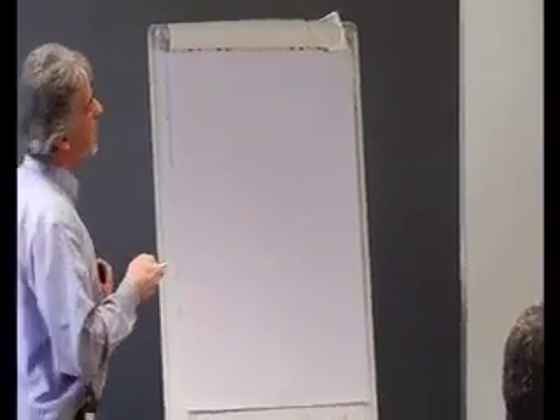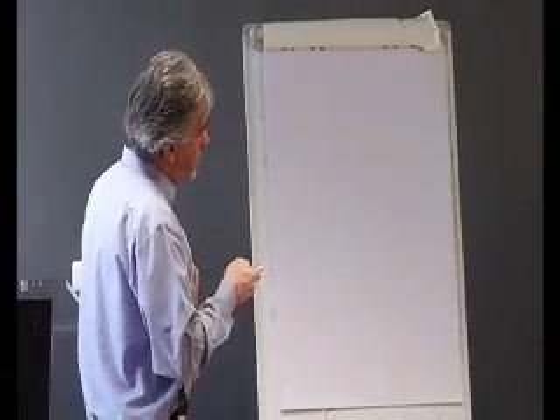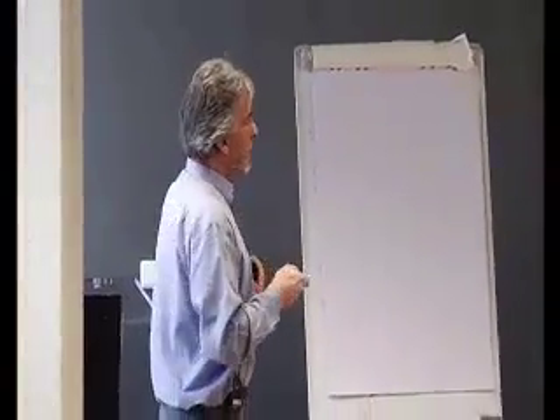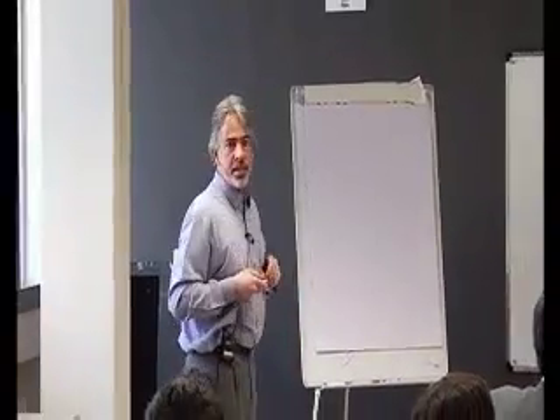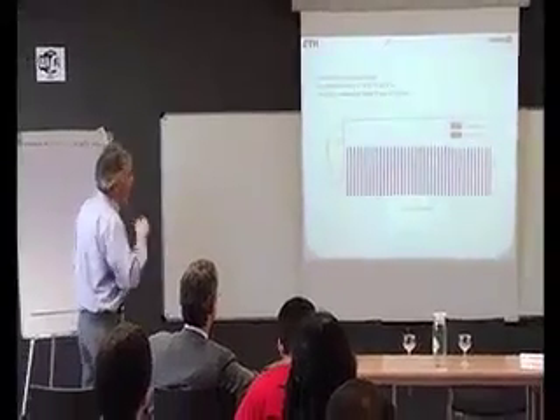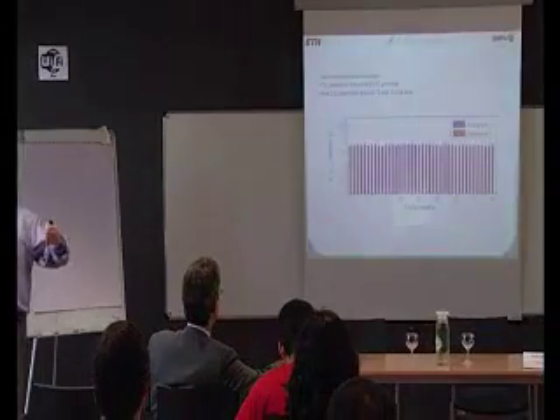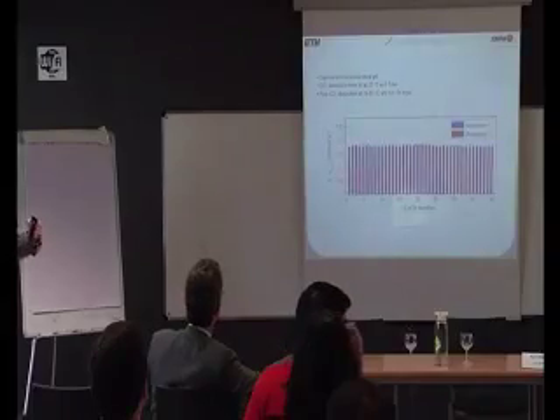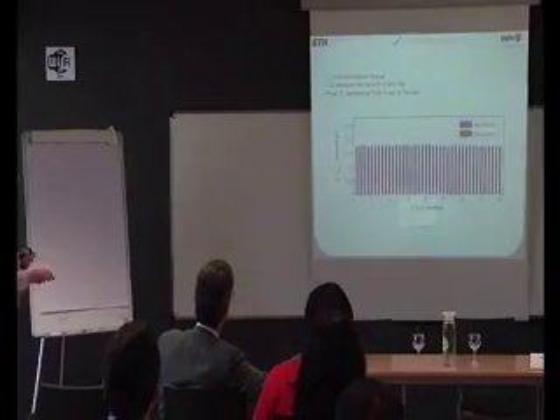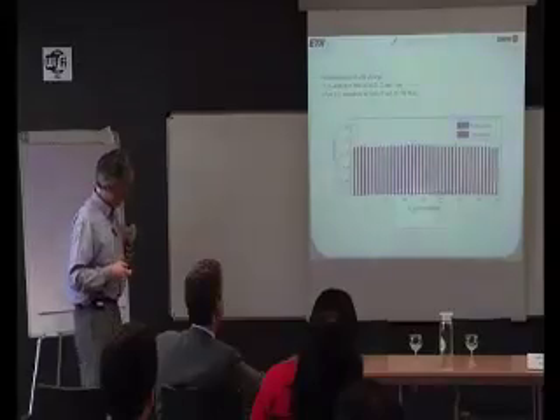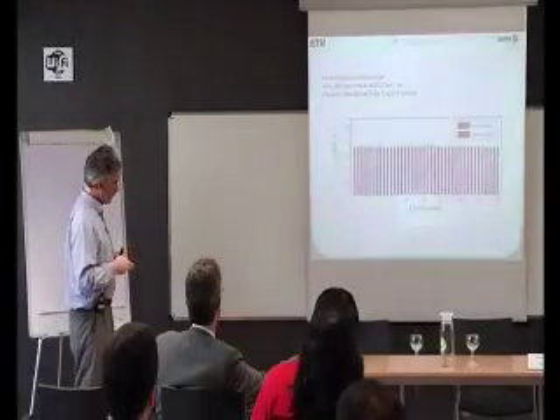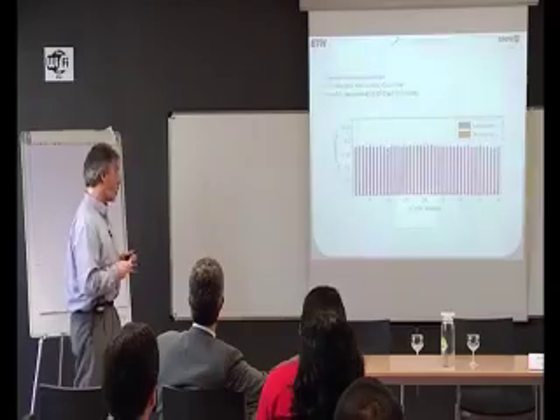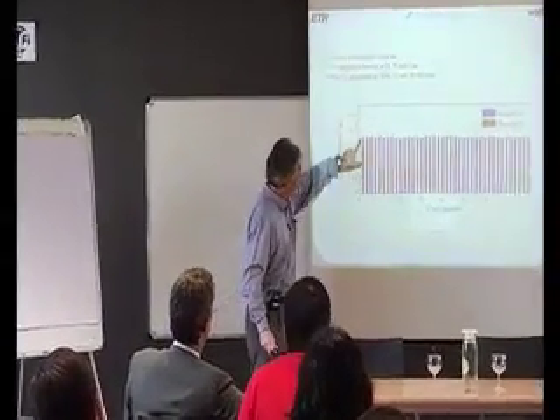So we have changed completely our approach, and now we are using a material that is based on amine functionalized silica gel. The absorption takes place at 25 degrees Celsius in 1 bar. And then we desorb at about 90 degrees Celsius. We have to pull a slight vacuum to make the reaction go. And here is an example of 40 cycles with this material, where we show the stability of the material, but we still need to improve the capacity.